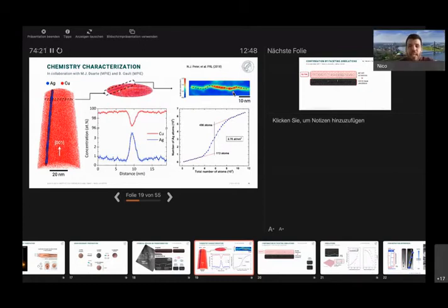Yes. So with atom probe, we have a problem because we don't see the atomic structure. Also, atom probe has a very good resolution in depth, so along this line going down here, but laterally the resolution is pretty bad. And this depends on the reconstruction that you use for your atom probe tip. Because of the curvature, you need to know where the atoms come from. And typically, if you have a grain boundary with some segregants, for example, silver has a different evaporation field than copper, so it does different things.